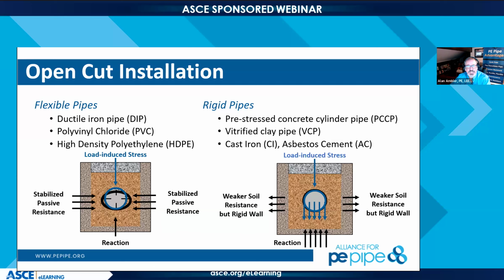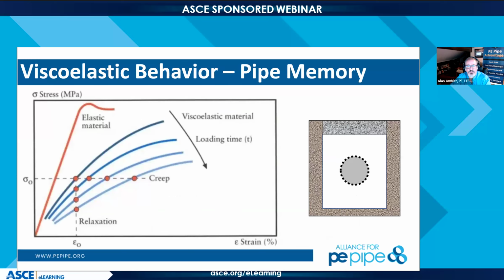So it's interesting to note that even though the hoop strength or elastic modulus of HDPE is significantly less than ductile iron pipe, the interface it makes with the stabilized soil surrounding it makes a big difference. Now, this is very different from a thick wall HDPE pipe, such as a DR7 or a DR11, all the way to a DR32.5, which is much thinner wall. And we've had some discussion about that thin wall non-pressurized pipe, and we'll do our best to continue with that. So, Brian, I'm going to go through this one while I want you to talk about it and elaborate.